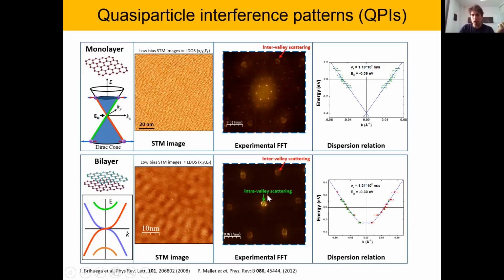In the case of bilayer, we see this ring which corresponds to intravalley scattering, but in the case of monolayer, this ring does not exist. So we are not sensitive to intravalley backscattering here. And this is because of how the pseudospin is in monolayer and bilayer graphene. So we are somehow sensitive to the pseudospin with STM. How the pseudospin rotates is reflected in the Berry phase of graphene, which is pi in the monolayer case, and 2 pi in the case of bilayer.